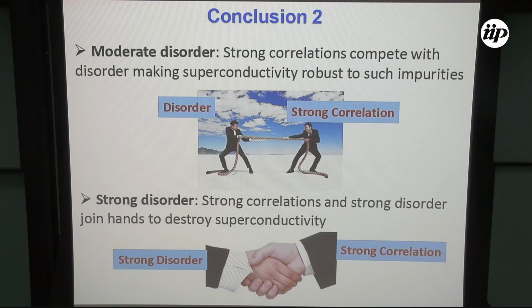So I would like to conclude by saying what was happening. This is the second conclusion for the second part. We still have competition. For weak to moderate disorder, disorder and strong correlation compete strongly to make the system robust to impurities. Superconductivity is then robust to impurity. If you increase the disorder strength such that you are above the bandwidth, then they join hands. They join hands by forming Mott sites and Anderson insulators, and then killing superconductivity jointly. So, thank you.